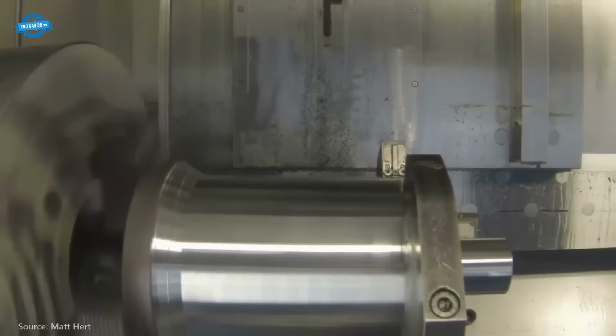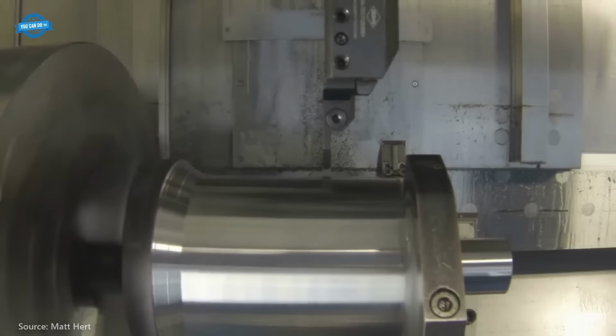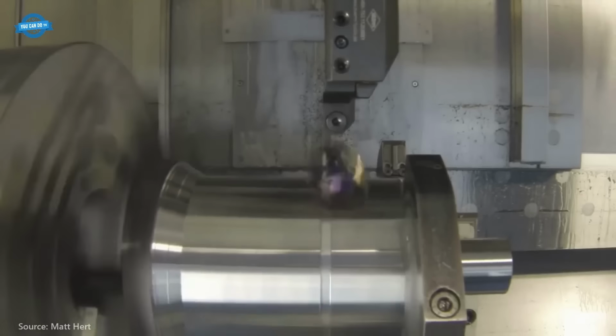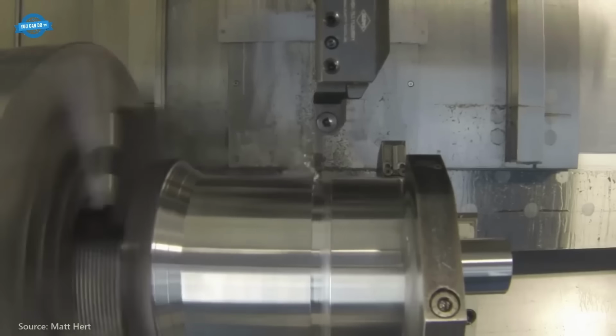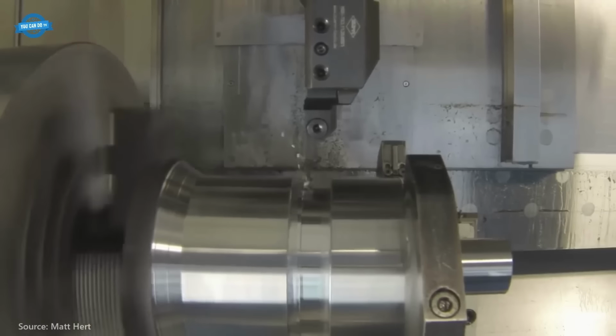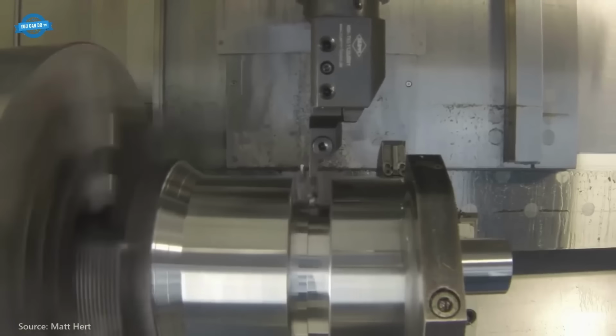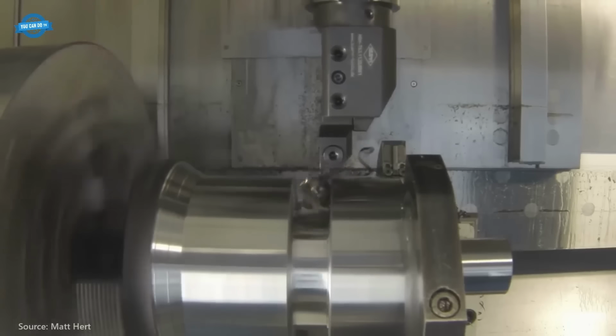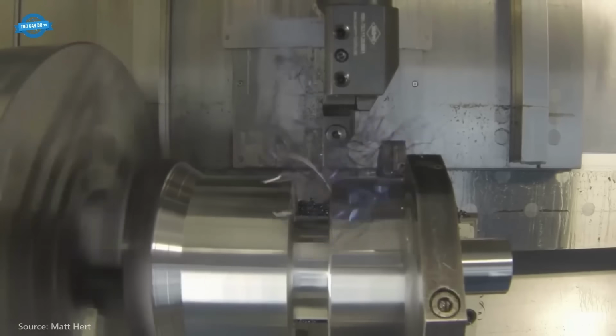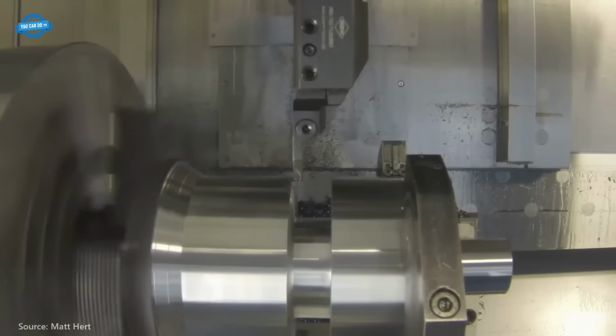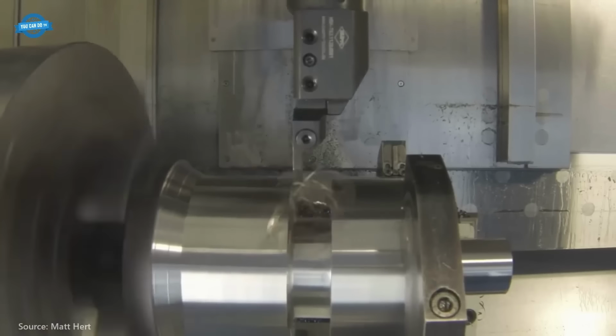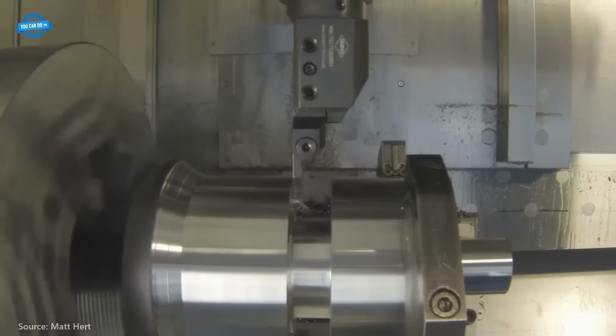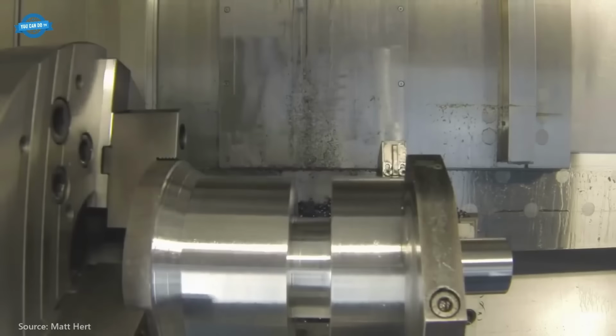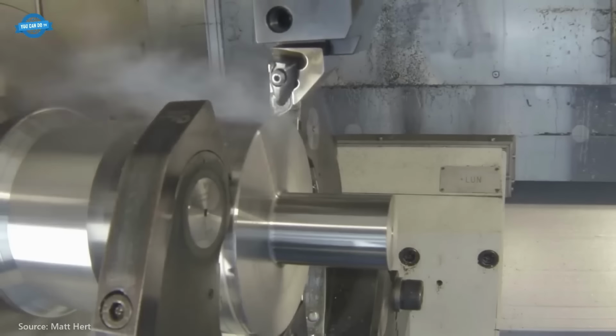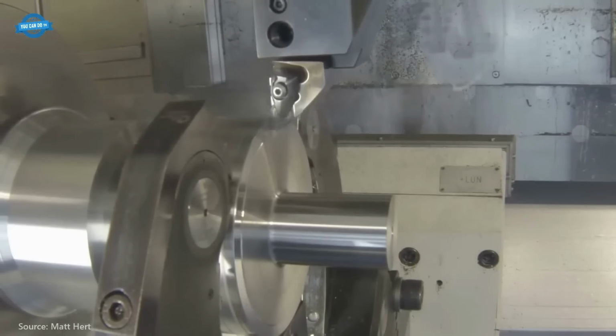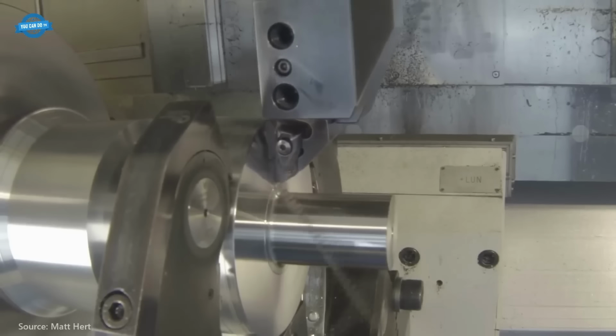Precision machining. Precision machining includes grinding, drilling, and boring operations. Grinding is used to achieve final dimensional accuracy and a surface finish of Ra less than 0.3 micrometers. Drilling and boring ensure precise oil hole and lubrication channel placements. The combined cycle time for grinding and drilling is approximately 60 to 90 minutes per crankshaft.